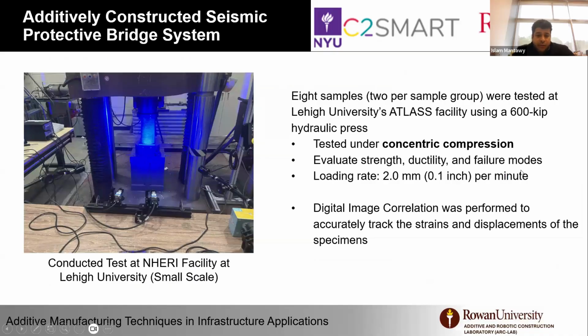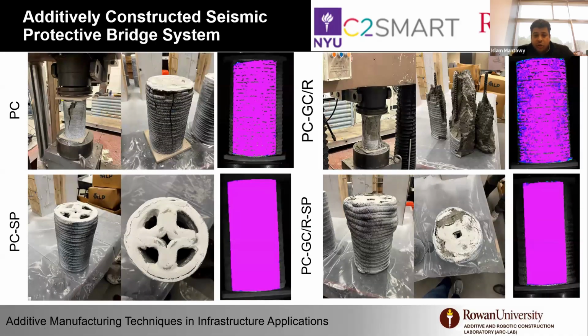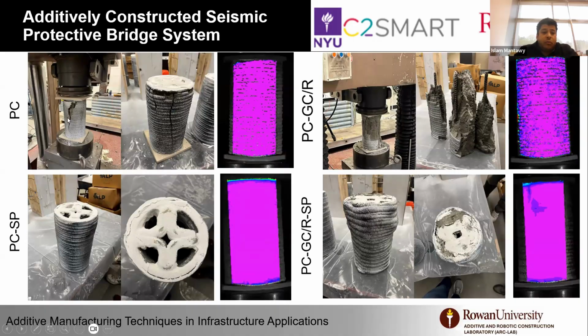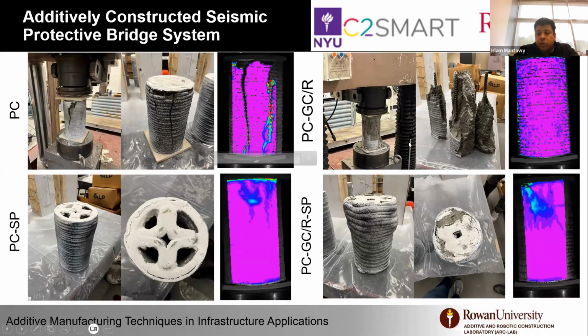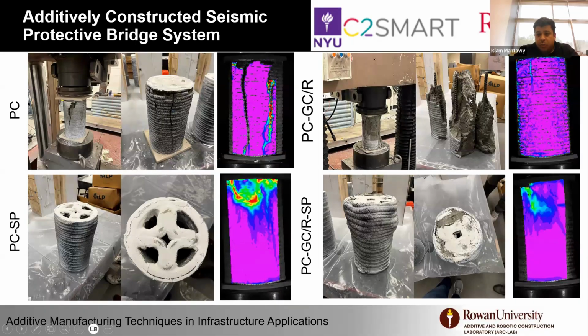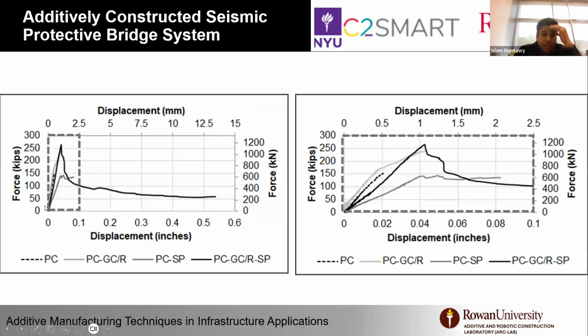We tested those at Lehigh University under a compression machine, a 600-kip compression machine that we are using. Here I'm showing the different failure modes we received, from brittle failure for no reinforcement, just a shell, to also brittle failure but with rebar inside, and also the one using the polyurethane material. As a comparison, we noticed that the column with the confinement showed more ductile behavior after reaching the maximum, compared to the one with no spray. We don't have the slide, but you can also see the increase in compressive capacity. This column was 6-inch diameter and carried around 250,000 pounds before experiencing any damage.